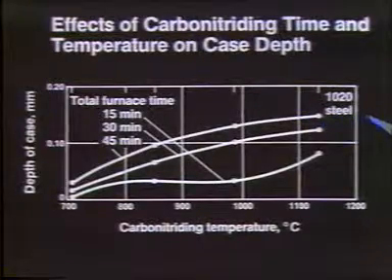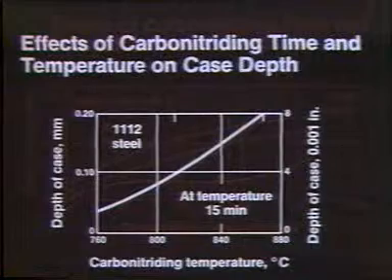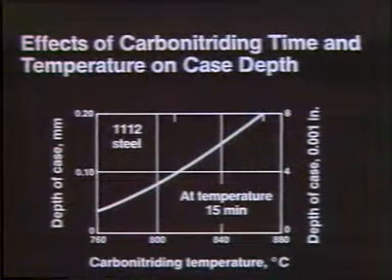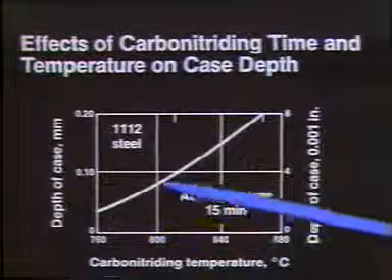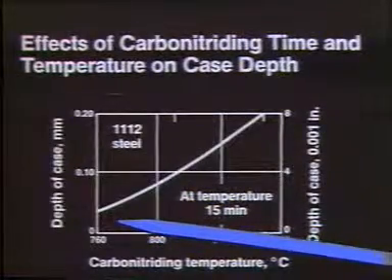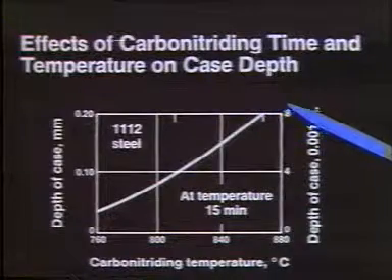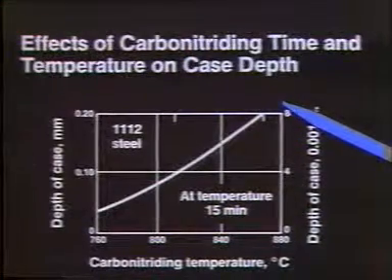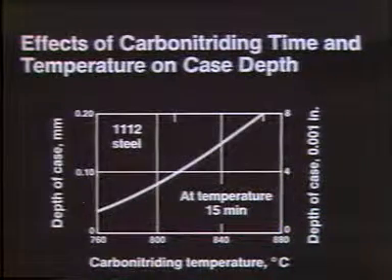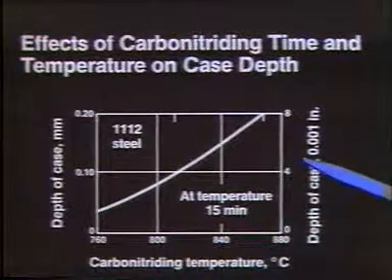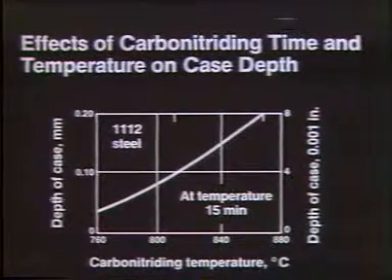If we did this for 11-12 steel, we find that the situation would be something slightly different. In this particular case, the depth is going up rather rapidly — in just a 15-minute period we have achieved about what we did in roughly 45 minutes with the other steel. So the alloy composition that we're going to use is going to make a lot of difference in the depth of penetration that we have.